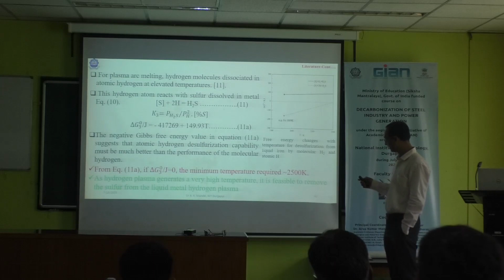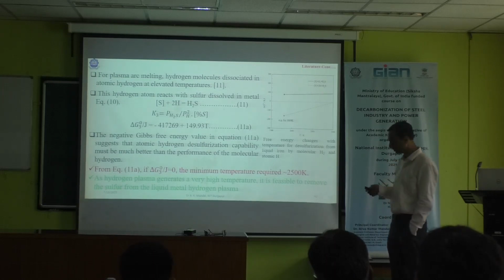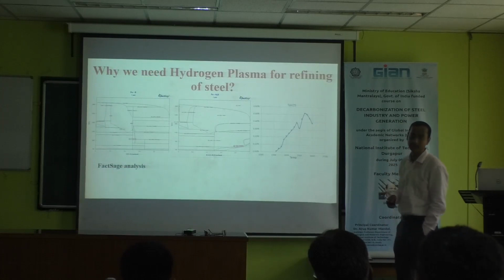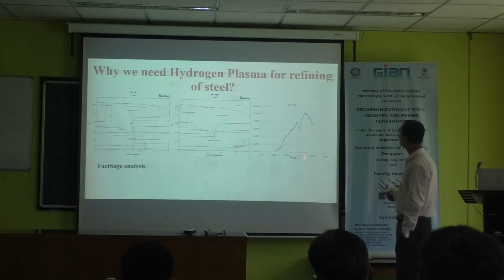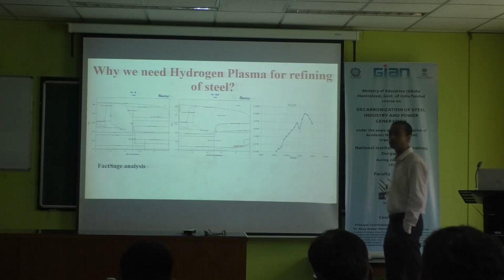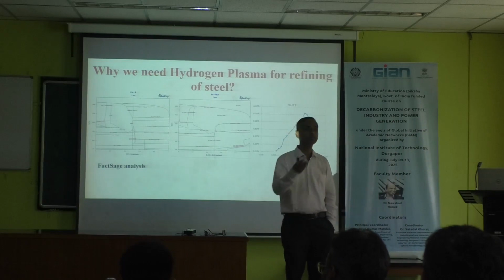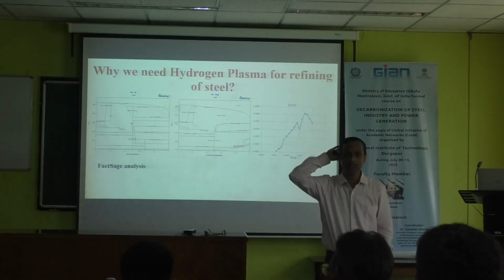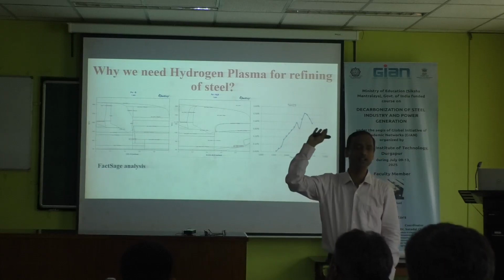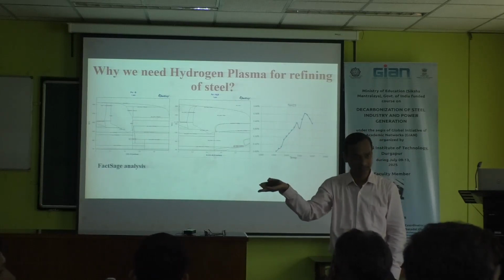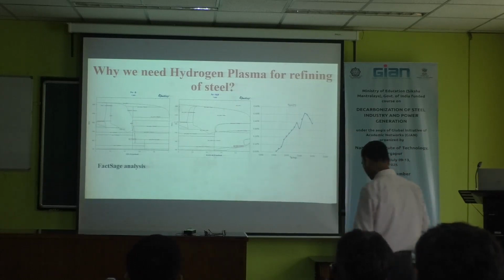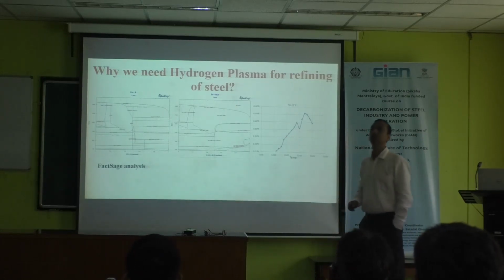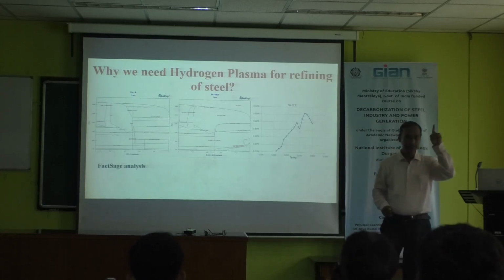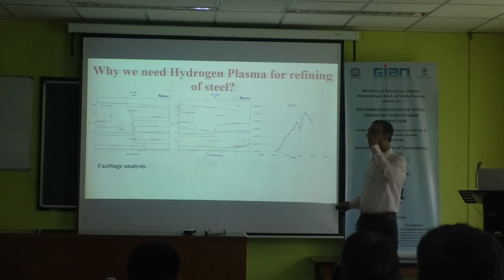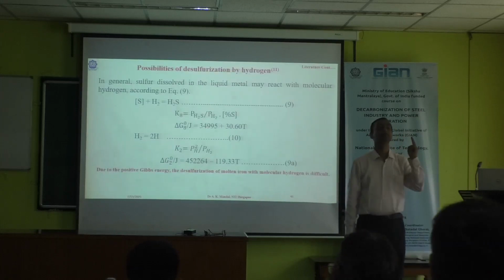And when it is possible, a very high temperature is required. I think you can see this much high temperature is required, which is not possible in normal steel making. Normal steel making temperature is 1500, 1550. In case of stainless steel, it is 1600. You cannot go beyond that. 2200 is required, more than that. Number one is high energy, high temperature. Number two, your hydrogen should not be hydrogen gas, because thermodynamically it is not possible to react.